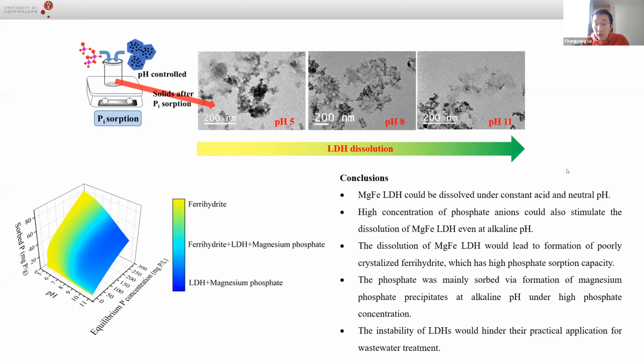I'm only showing one result, which is magnesium iron LDH, but other well-reported LDHs such as calcium iron or magnesium aluminum LDH also show a similar phenomenon. So we suppose that our finding has a general impact on a lot of LDH materials. If we want to use LDH in wastewater treatment or phosphate removal, we have to focus on how to increase the stability.